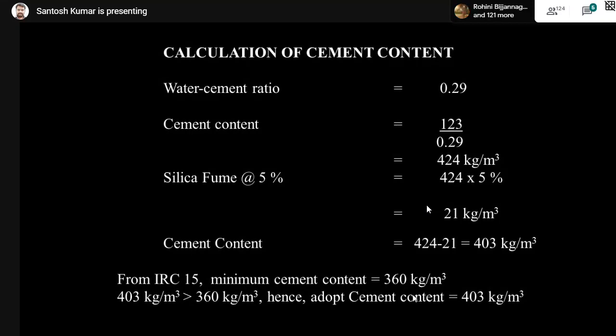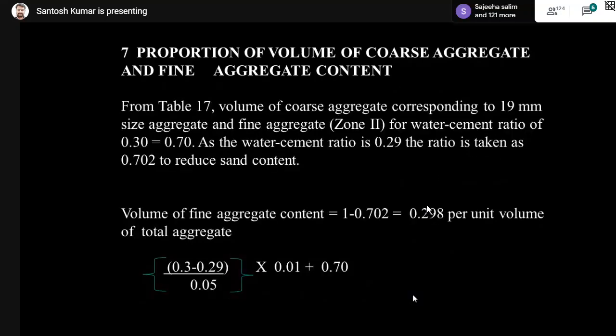In this case, being a high strength concrete, we are using silica fume at the rate of 5%. So 424 multiplied by 5% will give you 21 kg of microsilica. So 21 kg shall be removed from the total cementitious content of 424 kg. That means your pure cement content will be 403 kg and your silica fume is 21 kg per cubic meter. If you look into the requirements as per IRC 15, the minimum cement content is 360, which we are well exceeding, and 403 kg is greater than 360, so we can adopt the cement content as 403.